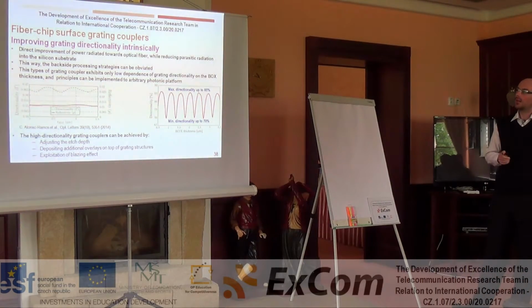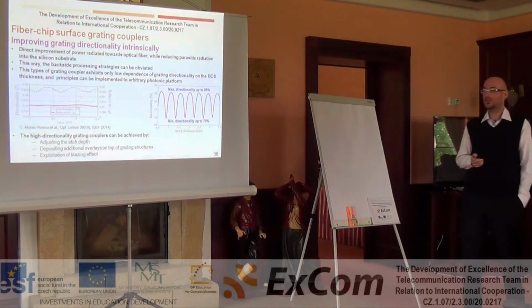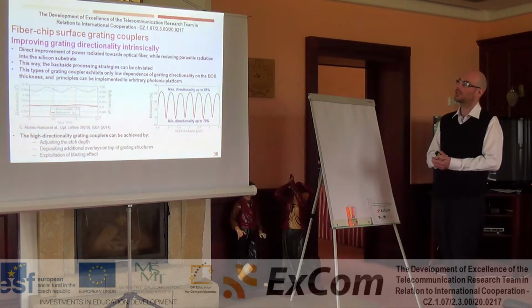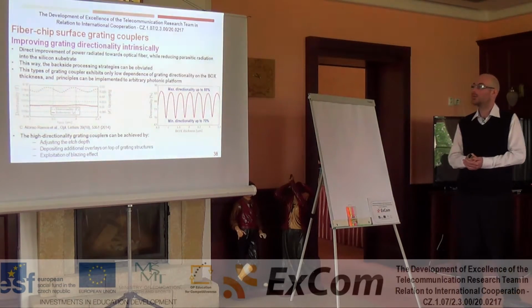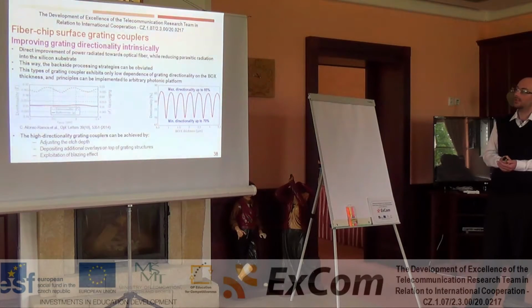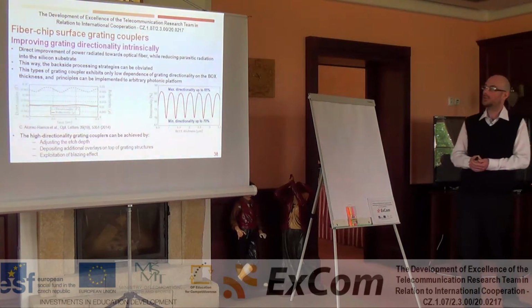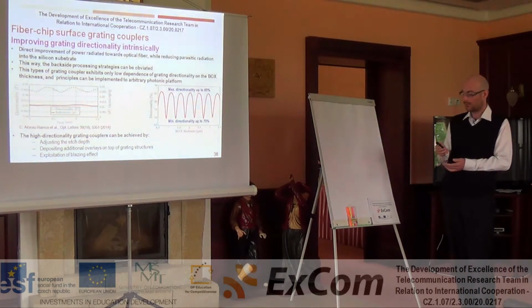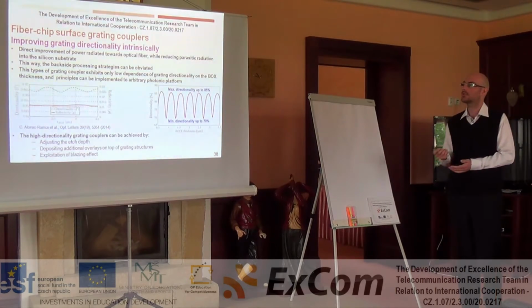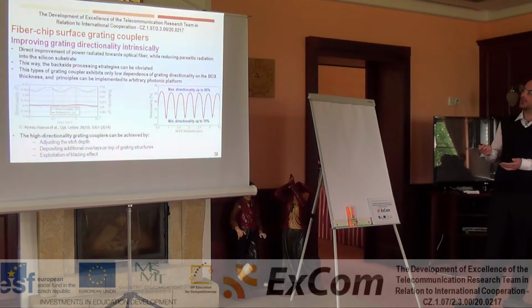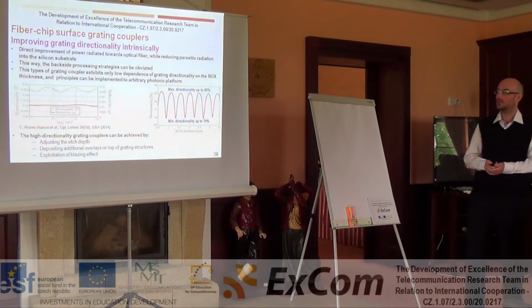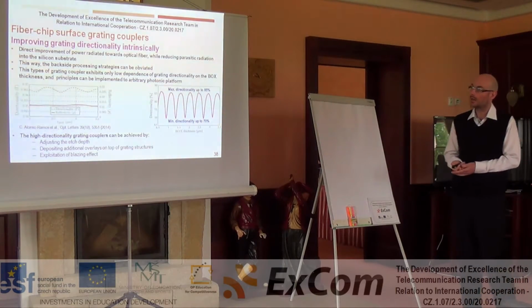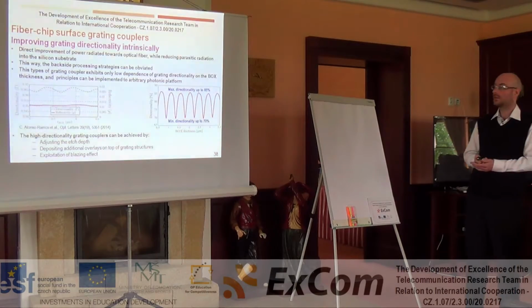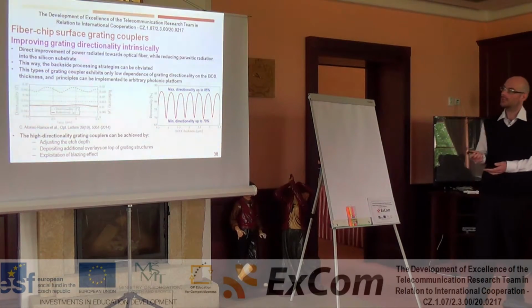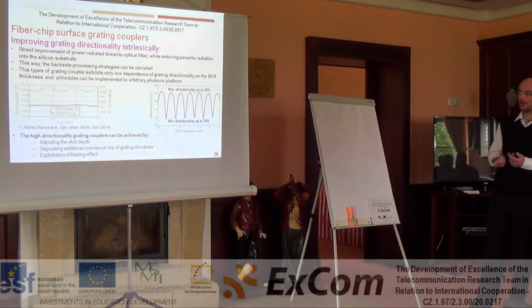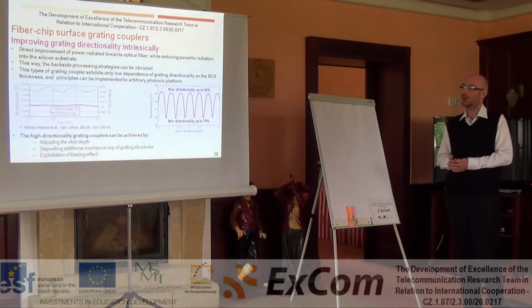There is an alternative way to achieve ultra-high coupling efficiency. In this way, we improve the grating directionality intrinsically. We achieve a direct improvement of the power that is radiated toward the optical fiber, and we reduce the parasitic radiation to the substrate. This way, we can avoid the strategies of backside processing or wafer-to-wafer bonding.